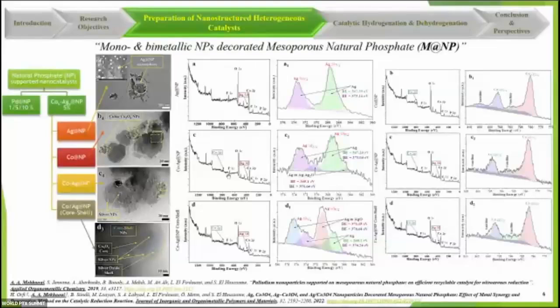The developed nanocolloids were used to prepare some supported catalysts, especially mono and bimetallic nanoparticles decorating mesoporous natural phosphate. We first studied the developed palladium nanocolloid and its deposition on natural phosphate at 1, 5, and 10% per weight. The optimized conditions were used to prepare other mono and bimetallic nanoparticles supported on natural phosphate, for example cobalt and silver nanoparticles. Through microscopic, nanoscopic, and structural studies, especially XPS, we demonstrated the synergy between both metals and the effect of cobalt oxide on silver. We have different silver oxidation states, depending on the preparation method.